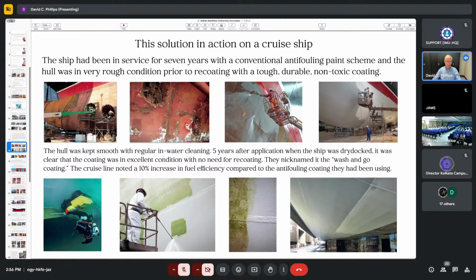They did. They cleaned it regularly, as much as they were sailing in hot water. So as often as 6 to 8 weeks, they cleaned the hull, preferably when it's only at the level of a slime or light weed, not a heavy fouling, because then you get the maximum fuel efficiency. If you clean it at about that stage, it cleans very easily. Each time you clean it, it actually gets a little bit smoother. You do not damage the coating, does not damage the environment. And here it is in dry dock 5 years later. And you can see this hull is in nice condition. It's not corroded. It's just been washed off in dry dock.